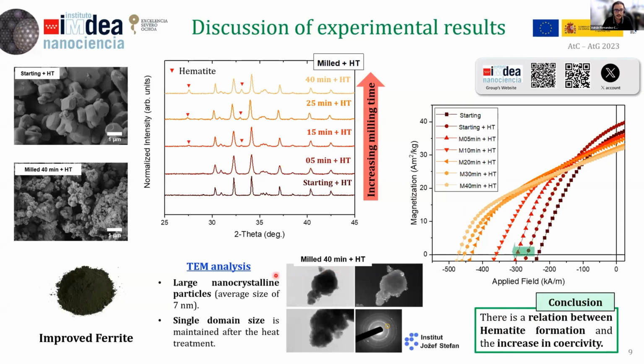We further analyze this system using TEM analysis. One of our partners in the project, Jozef Stefan Institute of Slovenia, made this analysis and managed to find, even in the extremely milled 40 minutes plus a heat treatment afterwards sample, large nanocrystalline particles with an average particle size of 7 nanometers.